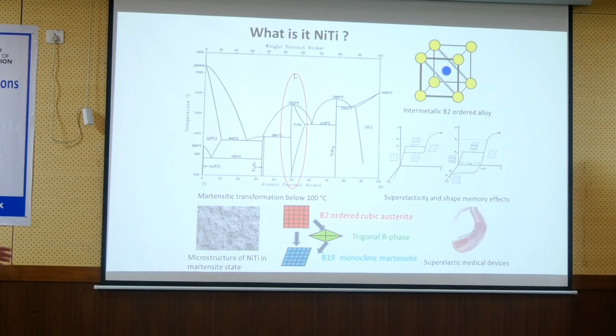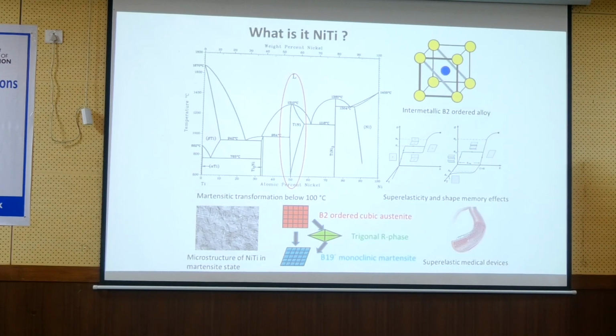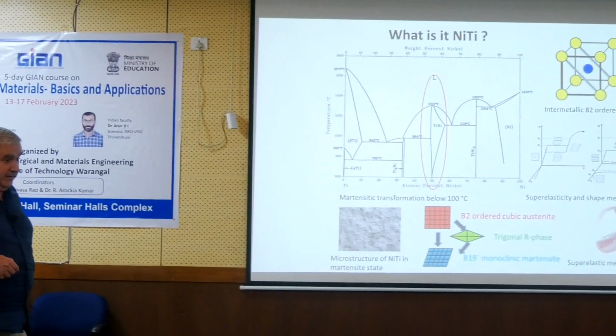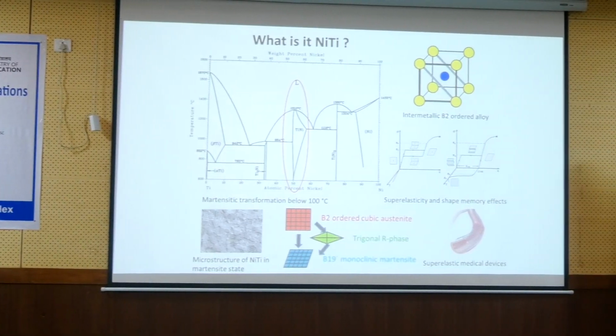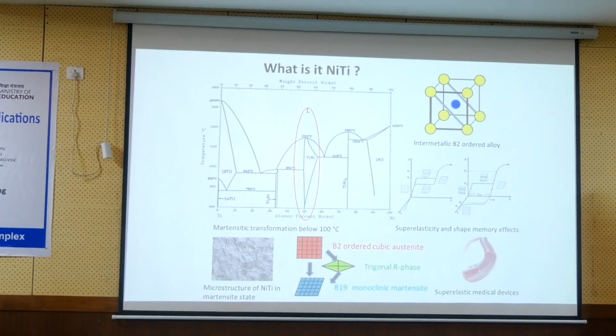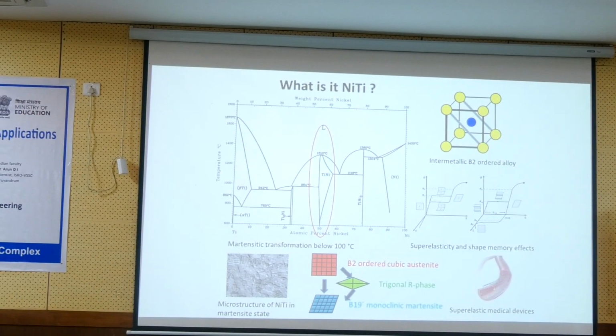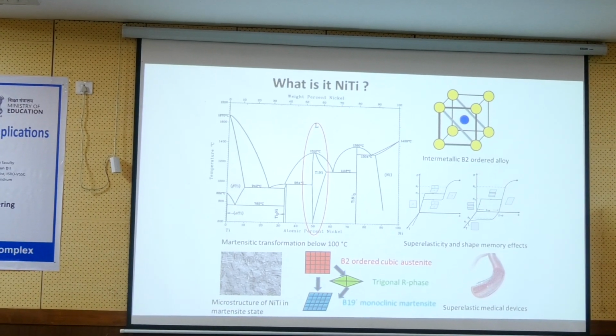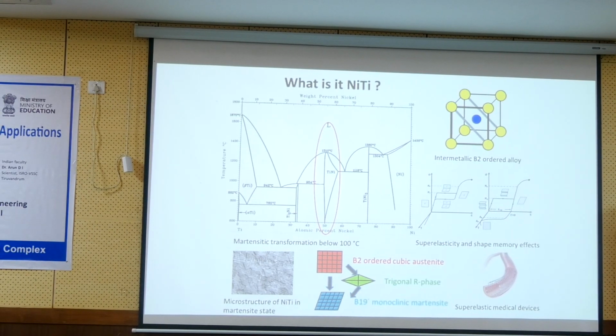The martensitic transformation temperatures are typically, as I said, below 100 Celsius. It can be 0, it can be -100, -200, but it's not possible to have binary NiTi with an AF transformation temperature above 100 Celsius, which is a problem maybe for actuation, because we are limited to low temperatures. Here in India in summer, if you have 50 degrees, actuation at 70 is not very convenient. In Czech, when we have 0 degrees, it is fine, but it would be better to have an alloy with slightly higher temperature, even for conventional applications.